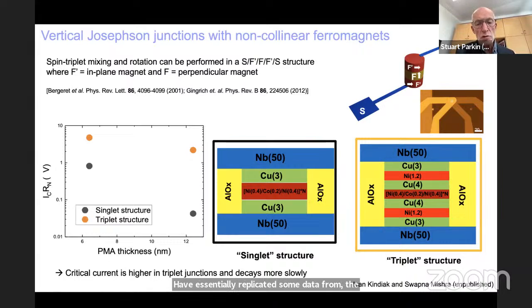And what they've shown is in a vertical Josephson junction, with superconducting layers formed from a conventional niobium shown in blue, then between the top and bottom electrodes shown in blue, they place a magnetic layer shown in red. The magnetic layer here is formed from the same material as in our racetrack, cobalt-nickel multilayers, which are perpendicularly magnetized. And then what they do is, first, very interestingly, that red layer becomes essentially superconducting, and we can pass a supercurrent from the top to the bottom niobium electrodes.